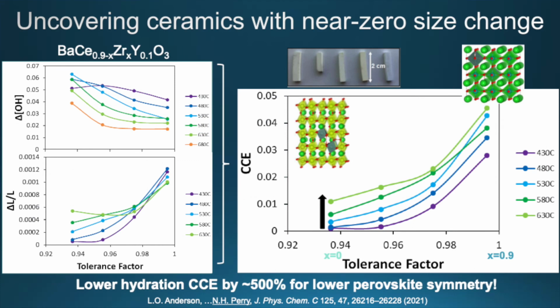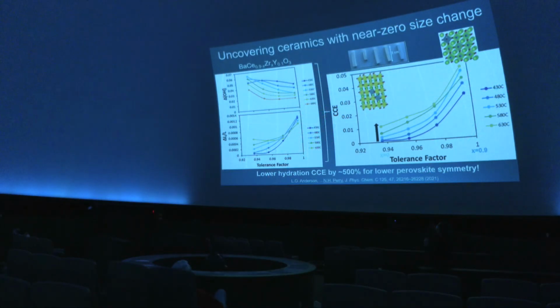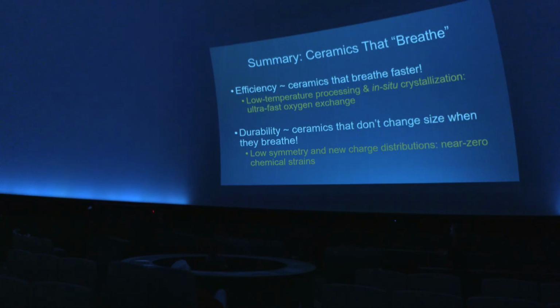Another example is materials that breathe steam instead of oxygen. So the ceramics that do that for different devices. And here what we found is we can get this coefficient to be, again, about 500% smaller if we distort the structure. Okay, so you can have a structure that has really high symmetry. Everything is aligned and in place. And then you can have a structure that's similar, but everything is distorted and not really in a regular position in the same way. And these distorted structures are also materials that hardly change size when they breathe. Okay, so that's a very quick summary of that part.